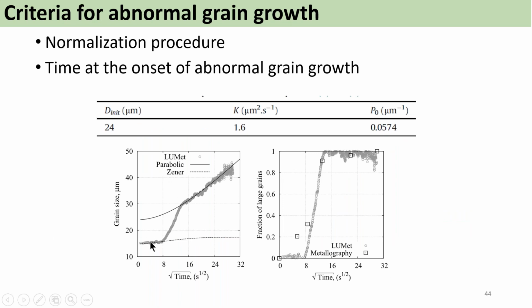So by doing this small modeling, we can actually determine the fraction of large grains and suggest to the industrial partner what is the time required for fully dissolving this precipitate in this alloy by one single test. We have to remind ourselves that this type of study requires a little bit of preparation, constructing a calibration, validating these measurements. But when this work is done, Lumet can be used as a single test to advise the industry, in a specific condition, on what time is required for fully dissolving the precipitate and recovering a homogeneous grain size distribution in the sample.